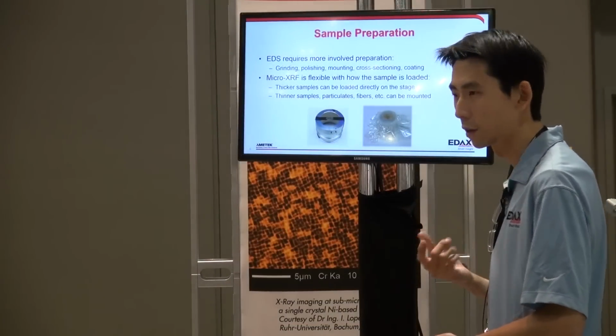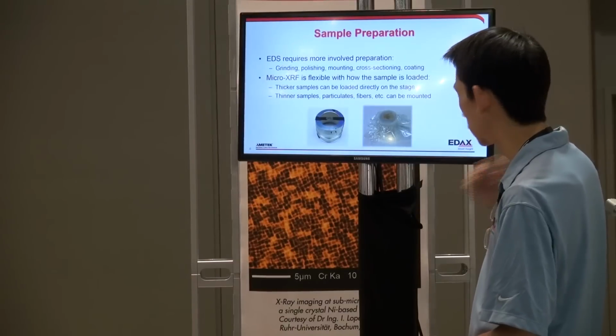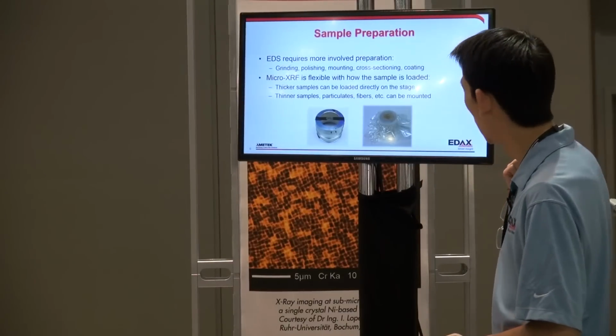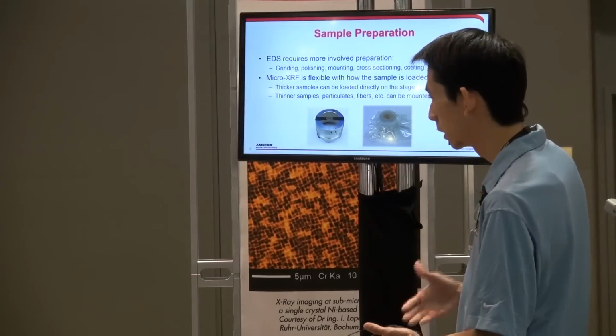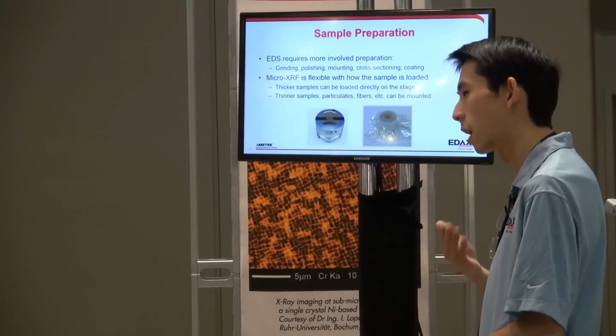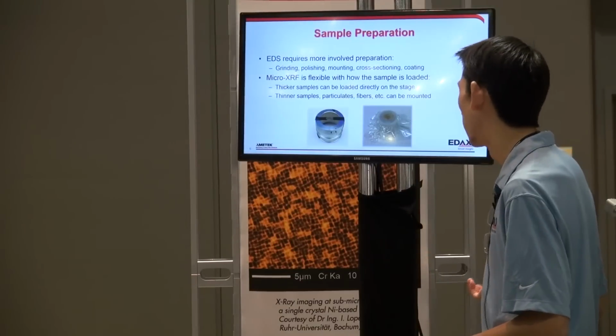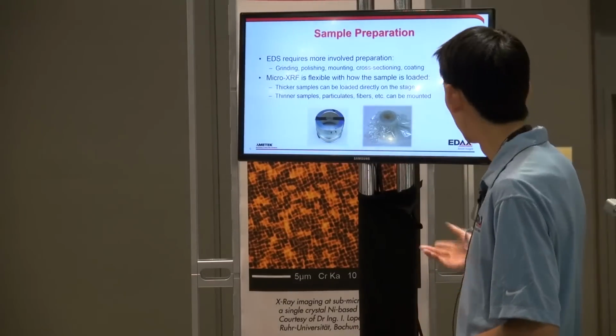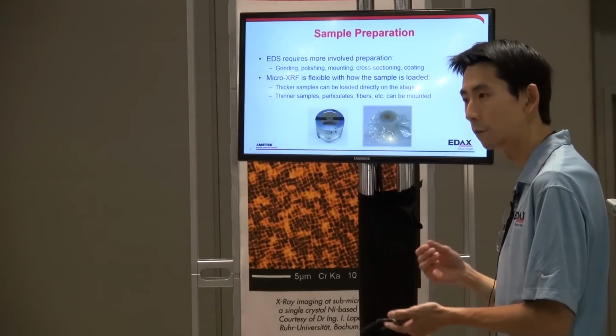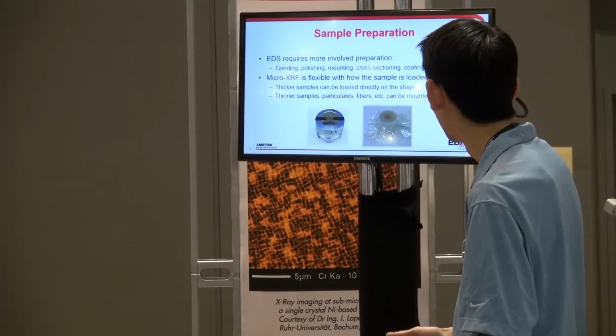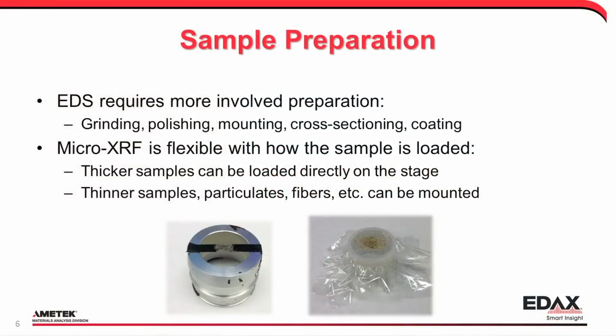These are just a couple examples of how we mount samples for analysis on XRF if the sample is not thick enough for a bulk sample to basically absorb all the X-rays. We can elevate them above the stage and kind of eliminate some of that scatter we would normally get from the stage top. One method is double-sided tape, or another one is just Mylar film in a sample cup with a clamp around it. That elevates it above the stage, eliminates scatter, and tries to optimize the signal from the sample alone. So that's optimal for thinner samples, particulates, fibers, powders, and so forth.